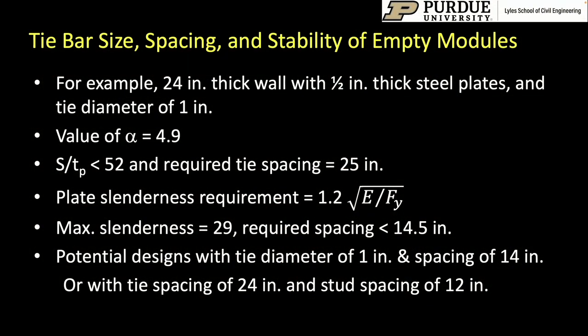So taking all of this information, I'm showing you here an example calculation for a 24-inch thick wall with about a half-inch thick steel plate and with diameters of the tie bars being about 1 inch. You go through the calculations, and what you find is that there are two design options that are possible. One is with 1-inch tie bars that are at a spacing of 14 inches. If you did that design, it would meet the requirements of the empty steel module before concrete casting. It would meet the requirements of local buckling and axial compression after the concrete has hardened as well. And at the same time, you would meet all the minimum requirements for the steel and the concrete.